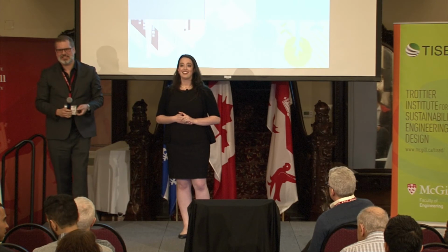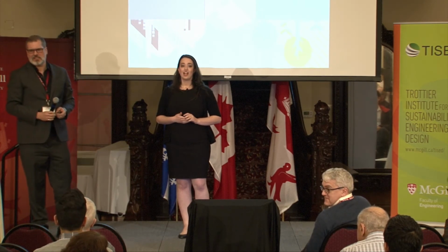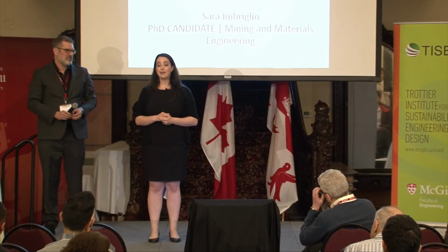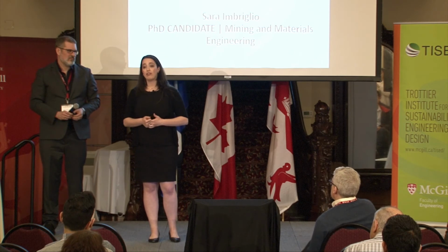Which one of the two ceramics has a higher porosity? They're actually quite comparable. I've cross-sectioned them, and they're sintered ceramics, so we're not seeing a significant amount of porosity in there. One thing that we did see, though, was that when we impact the silicon carbide, the interface tends to show more porosity, and that's probably because there's fracture occurring. So I don't think it's related to porosity necessarily, but I do think that the mechanical properties of the ceramic itself has more of an impact.